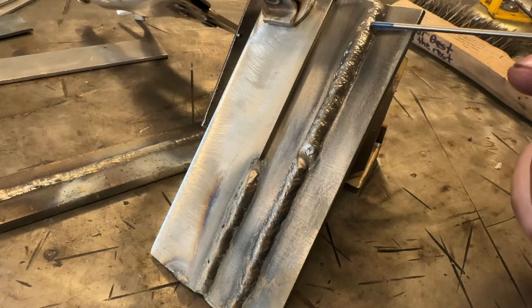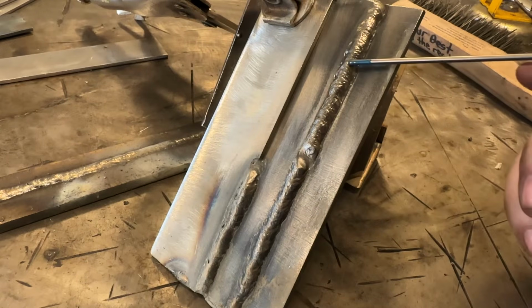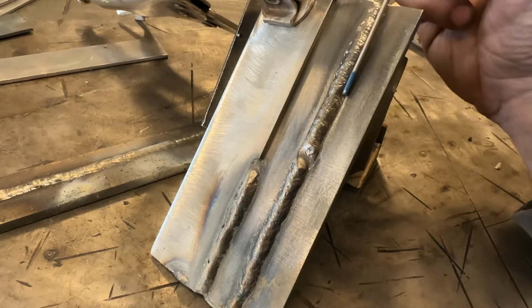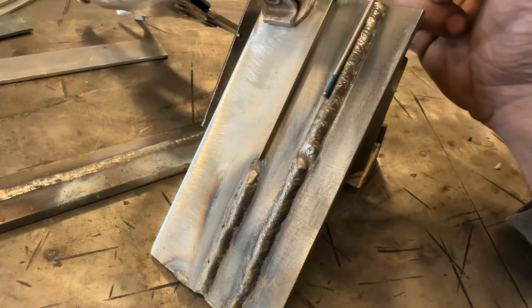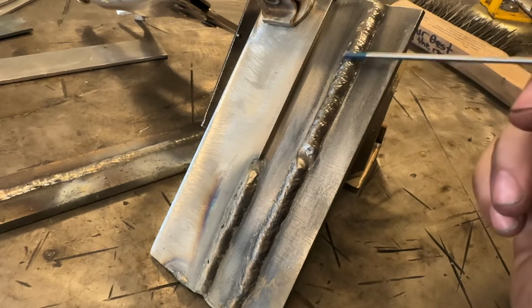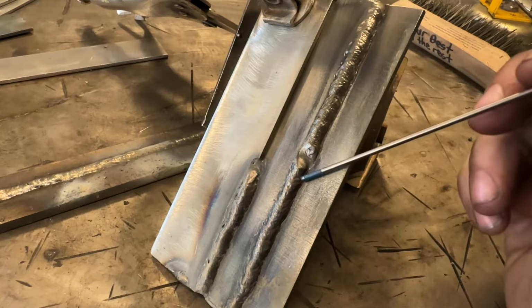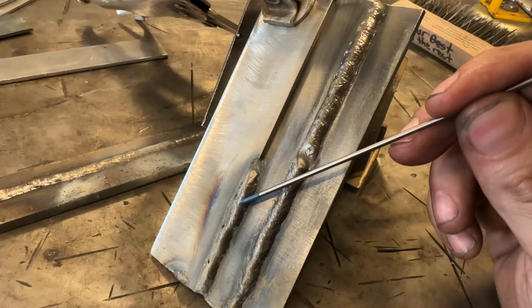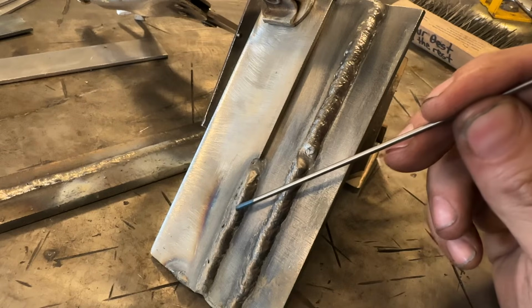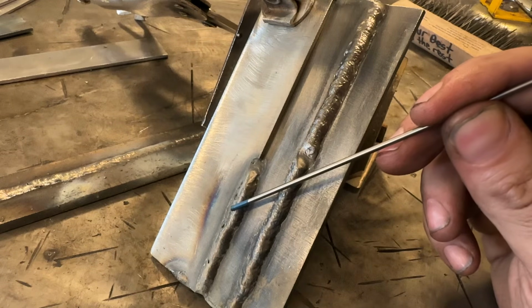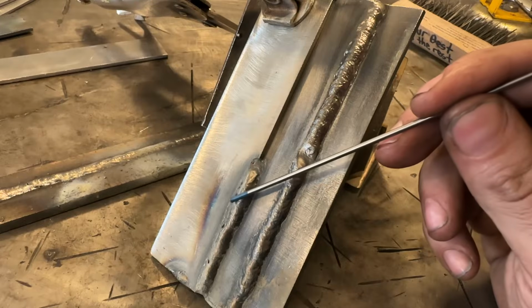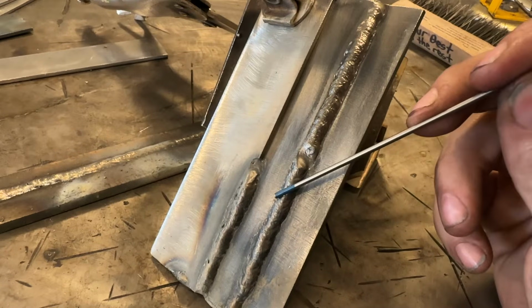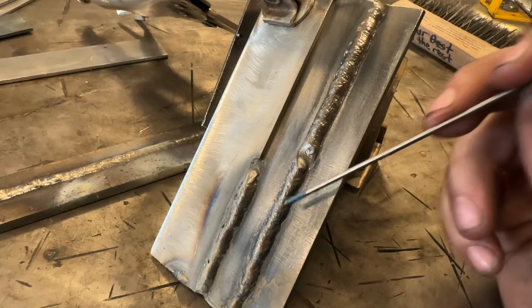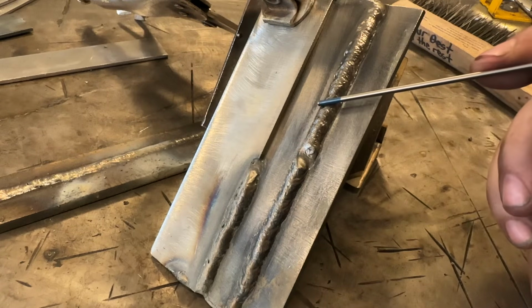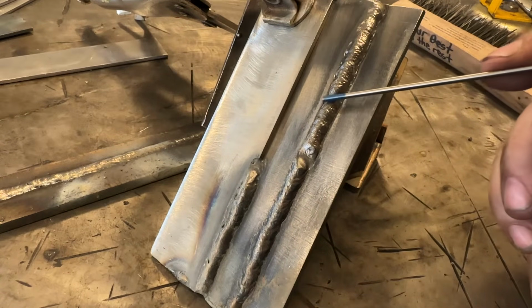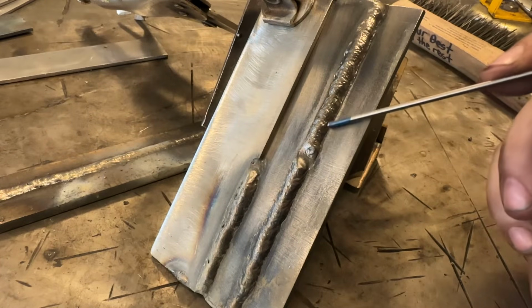This is a little bit inconsistent, but again, we're talking a very small weld here. I mean, we're maybe 2.5, 3 32nd electrodes wide, so not very wide at all. Again, first weld, cold, so too much wire, not enough voltage. Our metal to heat ratio, metal to voltage ratio was off. Here, a little bit better. Still off. Here, kept the same wire feed, and it's looking a lot better. This is more or less what you want to see.